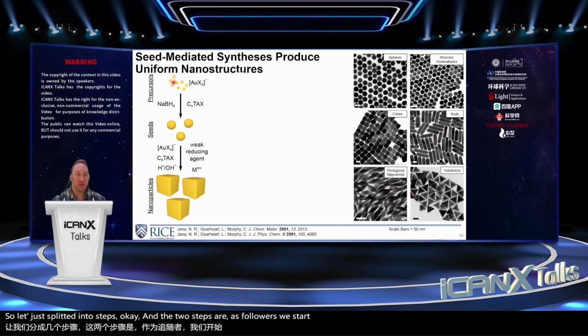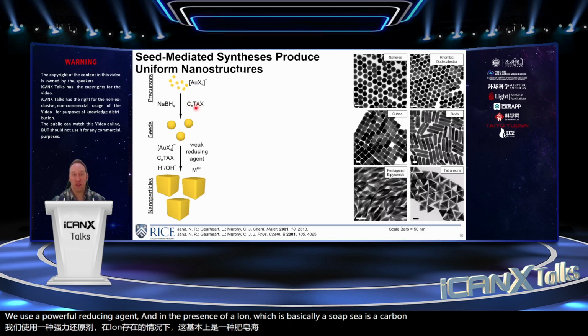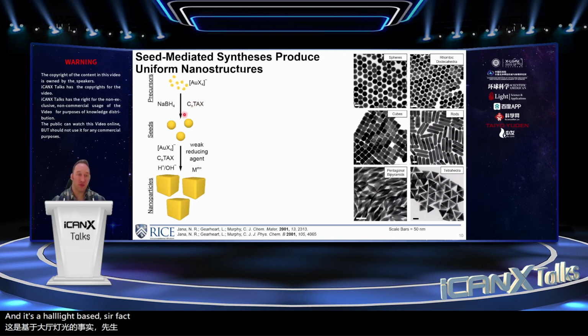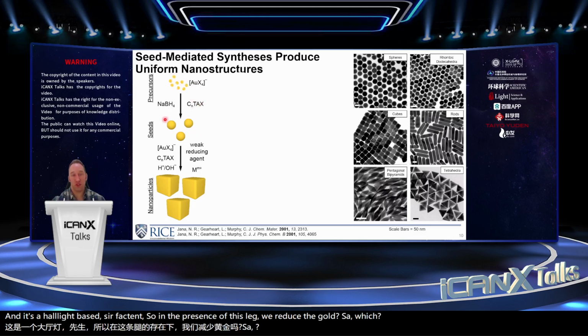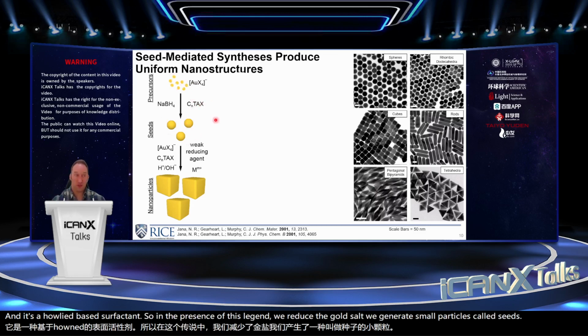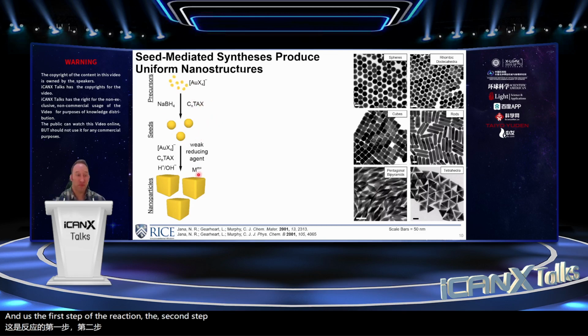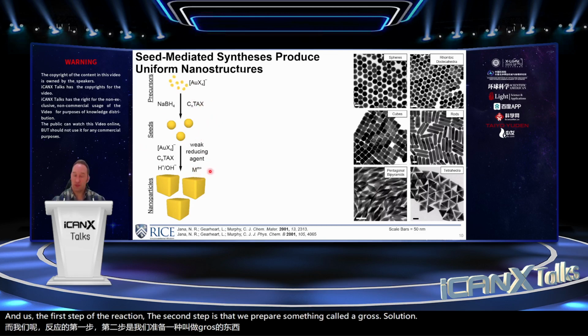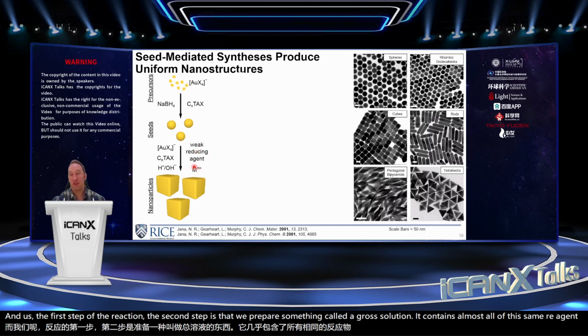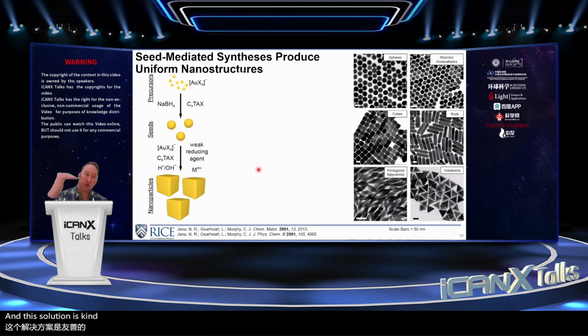We start with some solution of gold precursors, a gold halide salt. We use a powerful reducing agent, and in the presence of a ligand, which is basically a soap, where C is a carbon alkyl chain, N is the length of the alkyl chain, and it's a halide-based surfactant. So in the presence of this ligand, we reduce the gold salt, we generate small particles called seeds. Okay, that's the first step of the reaction. The second step is that we prepare something called a growth solution. It contains almost all of the same reagents. And this solution is brought right to the cusp of being able to homogeneously nucleate particles, but not quite. So it's kind of kinetically trapped.